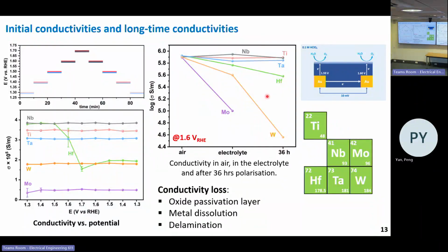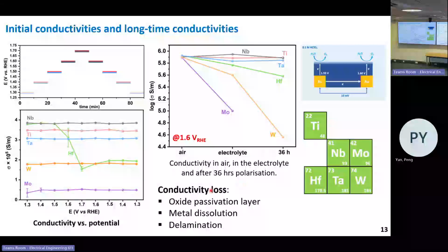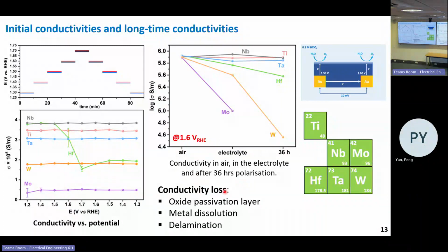And it's worth mentioning that the conductivity loss could be from the oxide or passivation layer on the metal, or the metal dissolution and the delamination of the thin films.